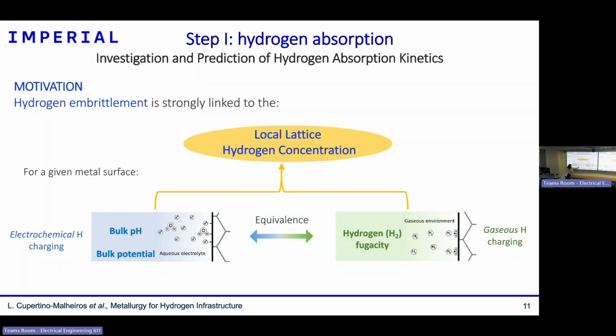The way we think about equivalence is that in the case of the aqueous electrolyte, the first step is actually producing hydrogen gas. So you're first producing hydrogen gas, and then part of this hydrogen is absorbed. So you could think of an equivalent pressure of hydrogen gas that will be produced in this environment, which would be equivalent to here, where you are actually exposing the metal to a hydrogen pressure. So that's what I mean by equivalence.